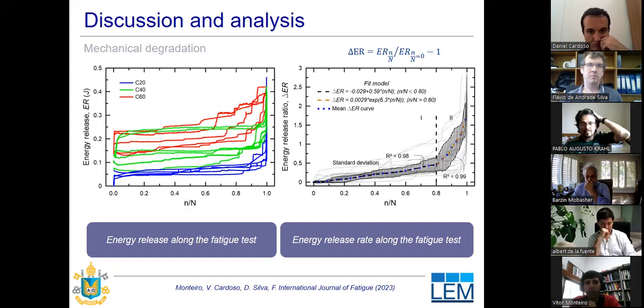A similar approach was done for the energy release. Once more, we have this correlation of flexural residual strength with energy dissipated. So we have more energy dissipated along the fatigue life when we have more fibers in the cracked section. And once more, we also made some empirical equations to verify this energy release along the fatigue life.